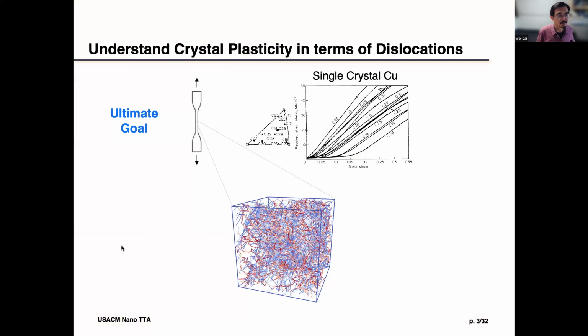So let me start by motivating and giving a general background of the problem that we're trying to solve, which is trying to understand crystal plasticity in terms of dislocations. What's shown here are single crystal stress-strain curves of, let's say, copper. A lot of those experiments were done in the 70s because people really tried to understand how we can explain crystal plasticity. We know that it is carried by dislocations. So the goal is to explain crystal plasticity in terms of the fundamental physics of dislocations.